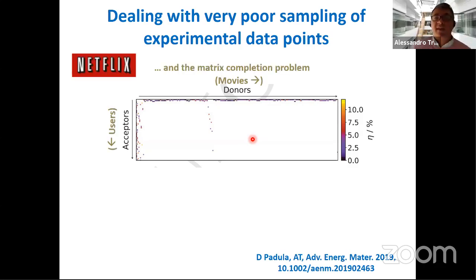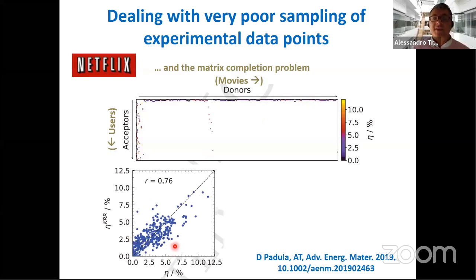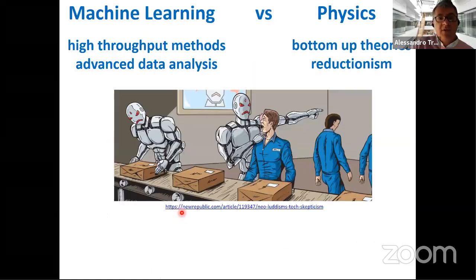And so this problem is essentially a problem that has been solved by Netflix, because in Netflix, they really want to predict as efficiently as possible what your favorite movies are, based on how you ranked the movies that you've seen and how other people have ranked the movies that they've seen, and the two sets do not overlap very well. So this is a matrix completion problem, and so you can use the same Netflix algorithm to make predictions of the solar cell made by a new donor and acceptor combination. And actually the prediction is better than the prediction where we only change the donor or we only change the acceptor. So I want to stop there about artificial intelligence.